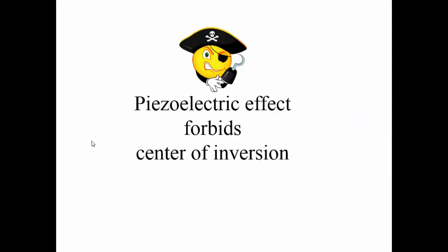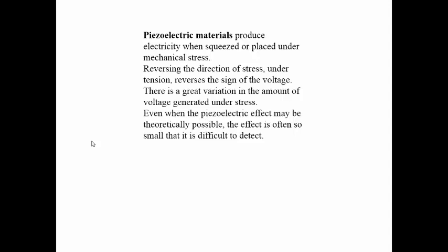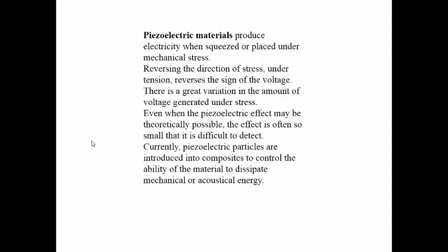Now we can turn that around and make use of it, and we can see how we classify materials according to their symmetries. So let's look at a few definitions. Piezoelectric materials produce electricity when squeezed or placed under mechanical stress. Reversing the direction of the stress, under tension, reverses the sign of the voltage. There's a great variety in the amount of voltage generated under stress. And even though the piezoelectric effect may be theoretically possible, the effect is often so tiny that you can't even detect it, so it's really not very useful in that particular type of material.